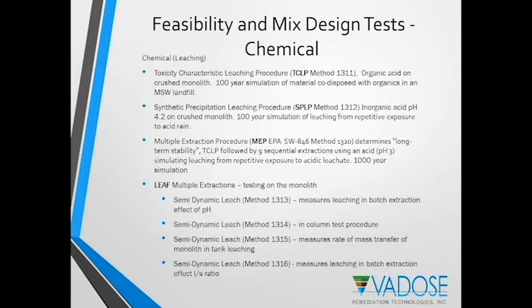The next test is the synthetic precipitation leaching procedure, or SPLP test, method 1312. This test uses an inorganic acid with a pH of 4.2, also on the crushed monolith. Now, that pH can be adjusted to be more representative of precipitation in a particular part of the country. This test too is intended to be a 100-year simulation to simulate the leaching from repetitive exposure to acid rain. So as you could imagine, this might be a more appropriate test to run if you're simulating materials that had been stabilized and left in place, rather than trying to determine if it is characteristically hazardous or not. So an SPLP test might be chosen instead.